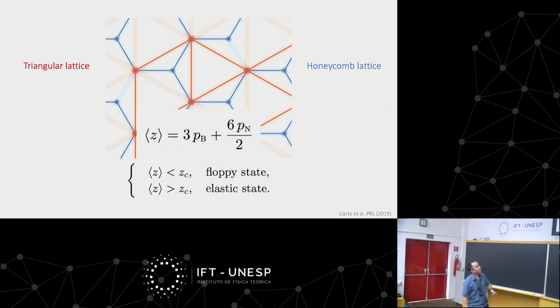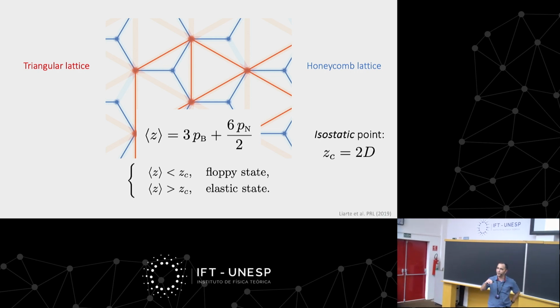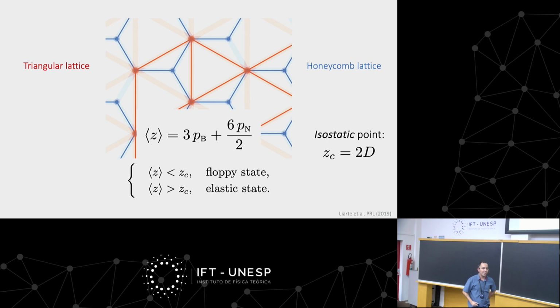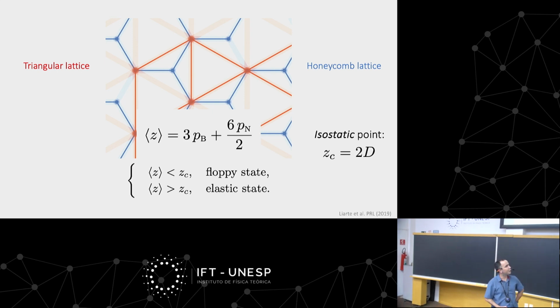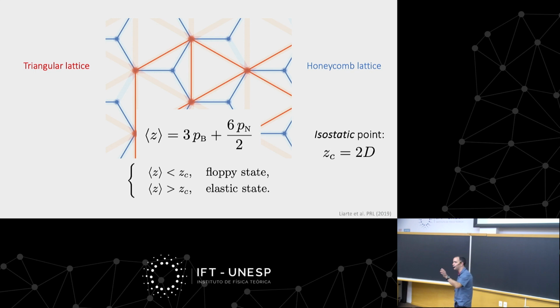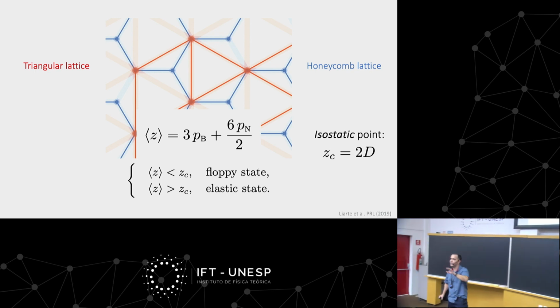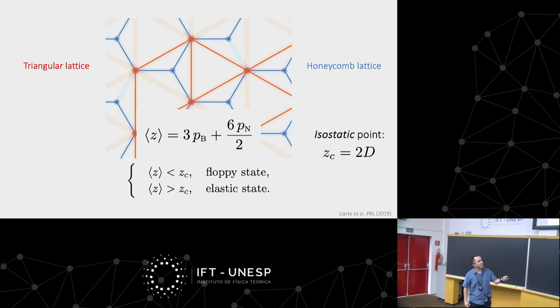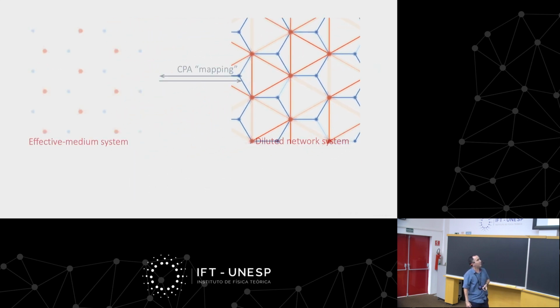So we were here. If average z is smaller than zc, you have a floppy state. If average z is greater than zc, you have some rigid elastic state. Now this is zc here. There is a very simple counting argument that you can use to calculate this critical coordination number, which was given by Maxwell a long time ago. It's just 2 times the dimension. You can just count degrees of freedom and number of constraints, and you find out that this is the isostatic point where this transition happens.